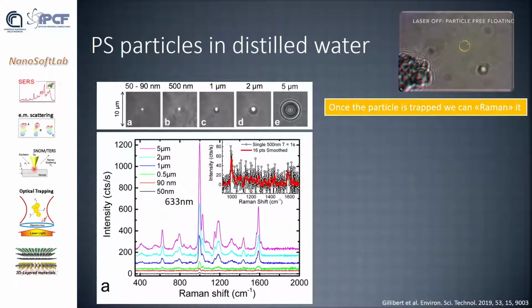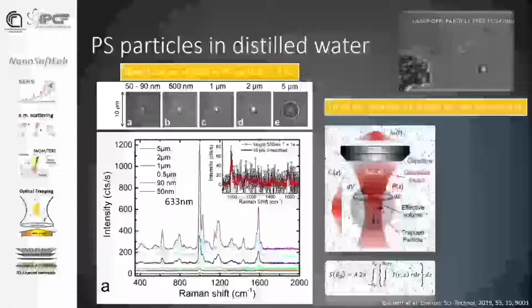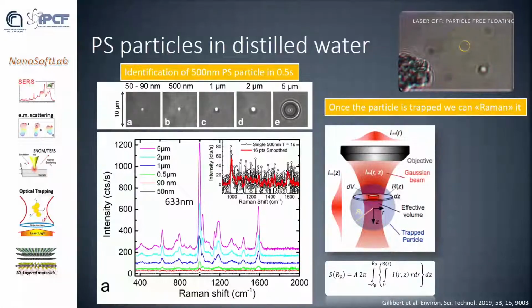Below you see the corresponding Raman spectra. You have more intense spectra as the particle is larger. What is important is that a 500 nanometer PS particle can be investigated in a short time, 0.5 seconds. So the technique can be quite efficient.